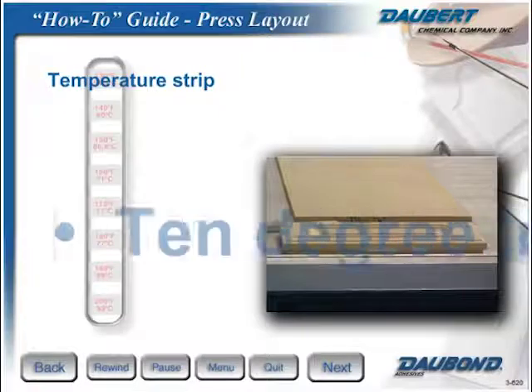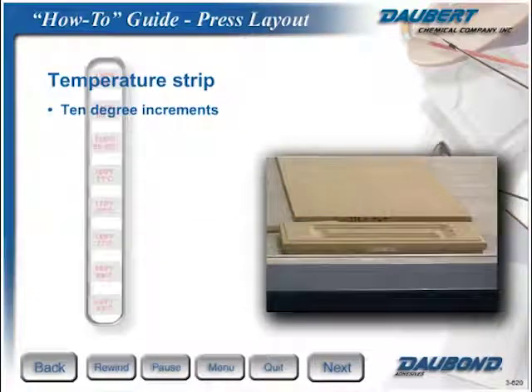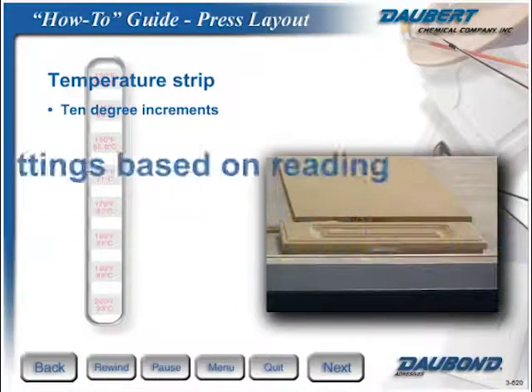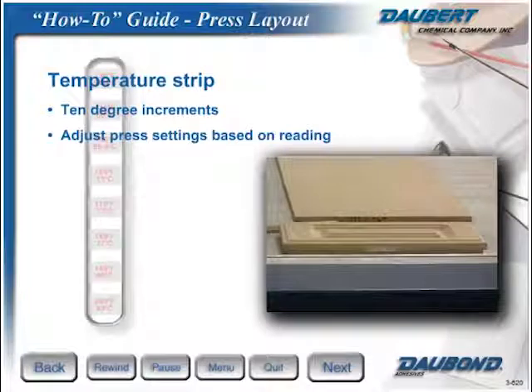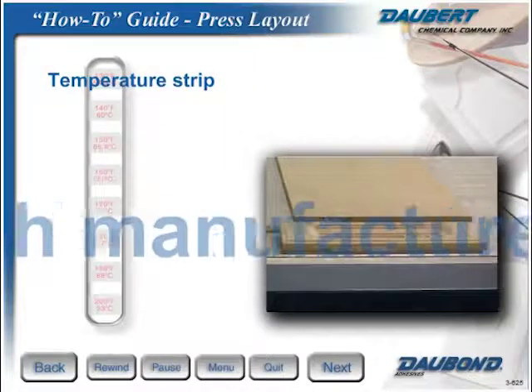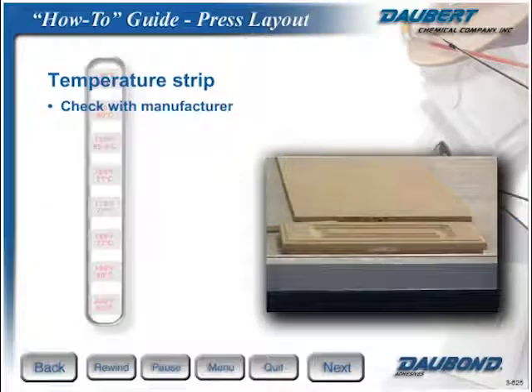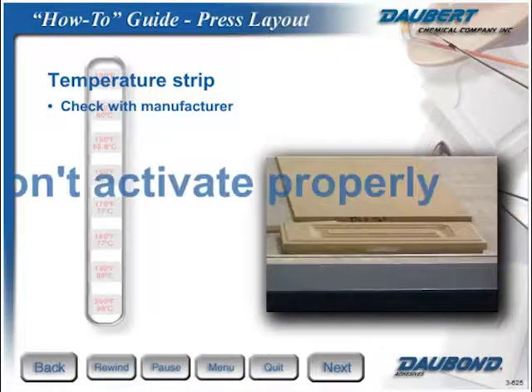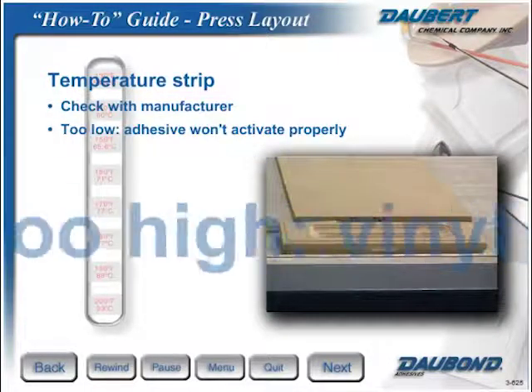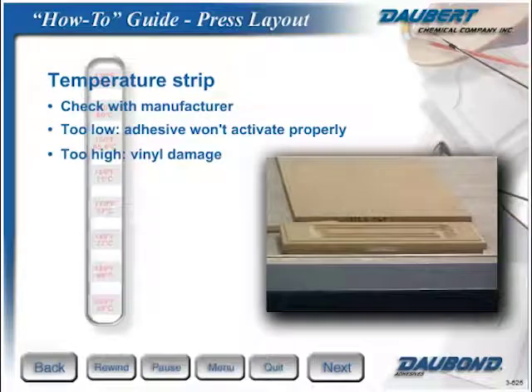Temperature strips are set up in 10-degree increments, usually from 130 to 200 degrees Fahrenheit. If your temperature reading is less than what is recommended, the press operator will need to adjust the press settings. Check with your press manufacturer and your Daubond rep on the temperature settings. They vary depending on your press. Too low a preheat setting and the adhesive won't activate. Too high a temperature and you can damage the vinyl during pressing.